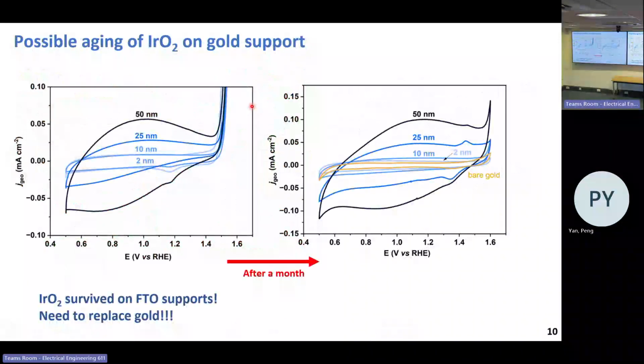What I found about gold is that the sputtered iridium can lose activity on gold after aging for a month. So that's the initial result, with very high activity. However, after a month, there's no activity, but the capacitance is still there. So it's really weird. But in the same batch of the sample, supported on FTO, they survived.